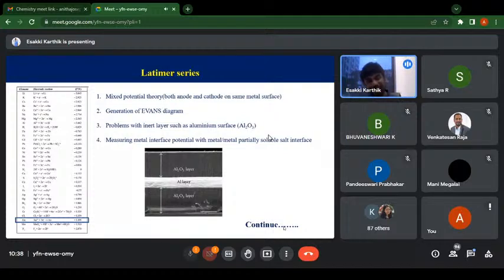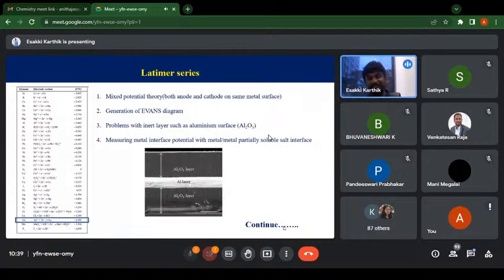But early on, when they started understanding corrosion, they tried to understand it with this Latimer series. But unfortunately, this Latimer series is not helpful beyond a particular level. Why am I saying this? In this Latimer series, you see aluminum. Aluminum has a reduction potential of minus 1.662 volt. It means aluminum can undergo corrosion very easily compared to other materials like iron, zinc. But in day-to-day life, in the real field, aluminum does not undergo corrosion as easily as iron or zinc. The reason is aluminum immediately forms an aluminum oxide layer.